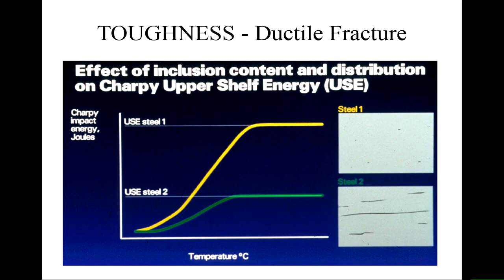If there's a bit more sulfur in the steel, the manganese reacts more. There's more of those inclusions. When the steel is rolled, which is done for making the pipe, those inclusions tend to form little lines. And then you see these large defects, and you get a very low upper shelf energy in that particular case. So the toughness has gone down. Small amounts of sulfur can have a big difference because of that.